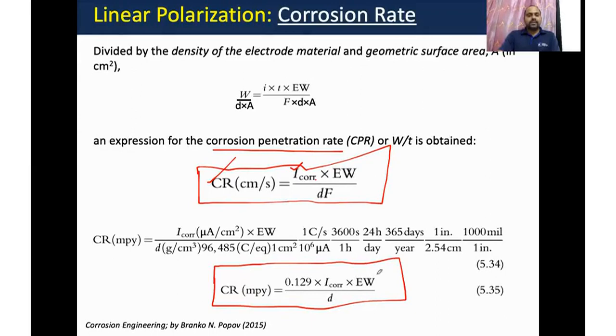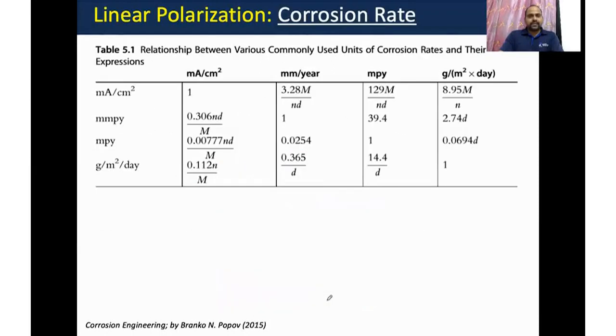The corrosion current is inversely proportional to the polarization resistance. Polarization resistance can be normalized directly into the corrosion rate. Usually linear polarization measurements are executed within 10 minutes. It's very fast. The current as a function of applied potential follows a linear trend, so the slope of the E-I plot is the polarization resistance. As you have already seen before, the current versus voltage plot is linear, and based on the slope of that plot we can calculate the polarization resistance.